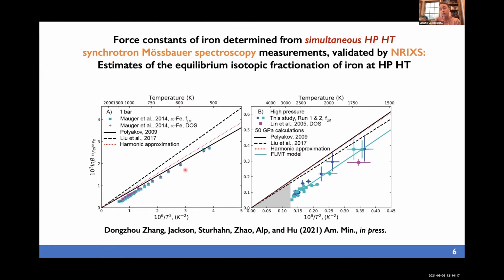And so from these measurements, we see that the force constants are affected by temperature. And if one wants to estimate the equilibrium isotope fractionation of iron from this new knowledge, it's about a 0.1 per mil effect lower compared to using room temperature NRIXS measurements and extrapolating using the harmonic approximation. So this is an observation we made utilizing synchrotron Mössbauer spectroscopy in a different way.